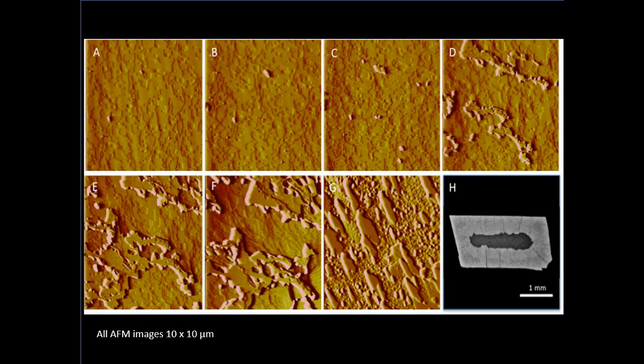Is this just a superficial reaction? Look at the number H. This is where I took a little crystal of calcite, I put it in exactly the same solution, made a section, looked in the SEM, in backscatter SEM, and you see an interface, just like with my salt solutions. The calcite is pseudomorphed in a new phase. It's a phosphate phase, a calcium phosphate, and after a few days, it actually does end up being a carbonated apatite. So we've got the original pseudomorph formation of a new crystal composition.